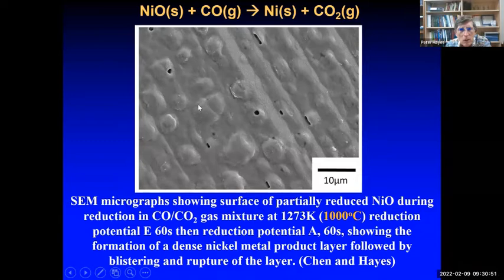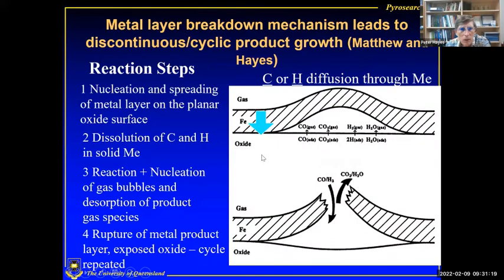and we can see that in this case we formed dense nickel, and what you see here are these round circles. These are the bumps, if you like, which have formed in the surface, and in here we can see holes, which is a bit like mini volcanoes, which have actually burst through and broken the layer down on the surface. And we see this type of reaction happening in the case of iron oxide as well as nickel oxide. And here what happens, so the gas gets separated from the nickel oxide, but carbon can diffuse through the metal layer, react with the nickel oxide and form gas here, and that blisters and eventually bursts that layer and allows the gas to come in, and the whole reaction starts again.